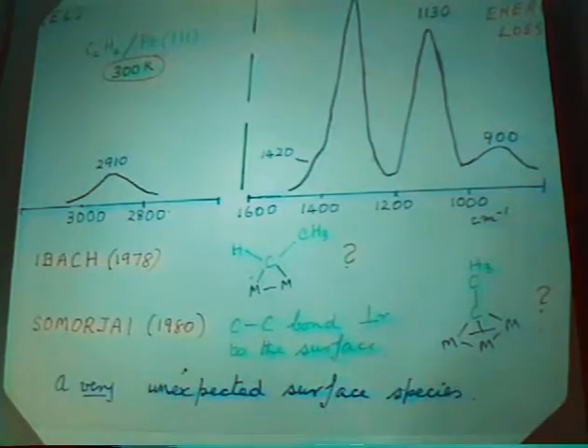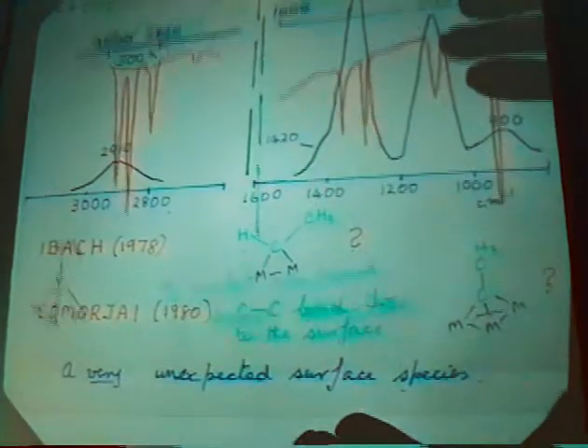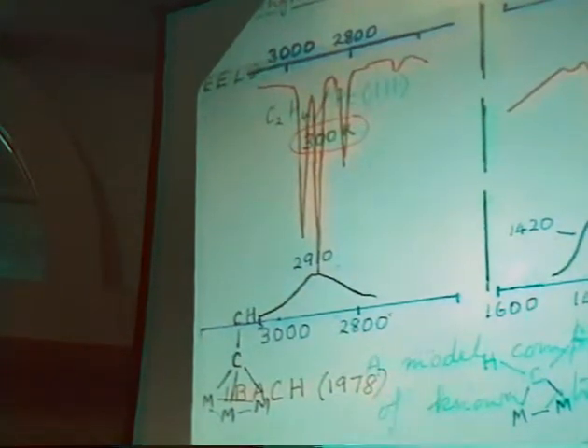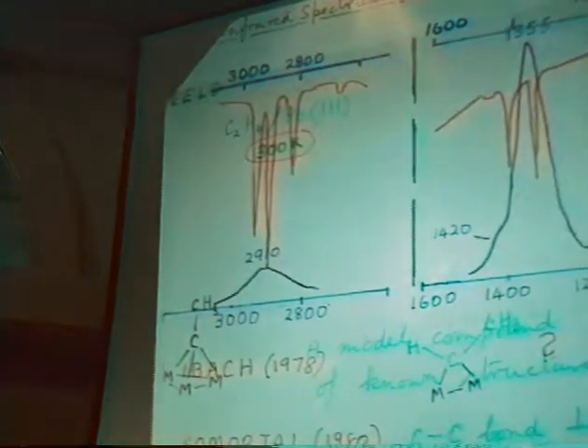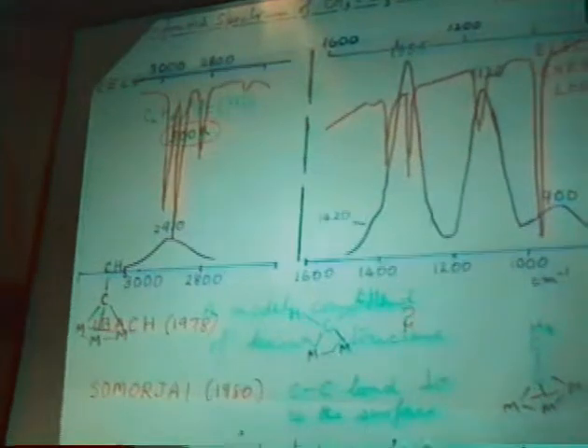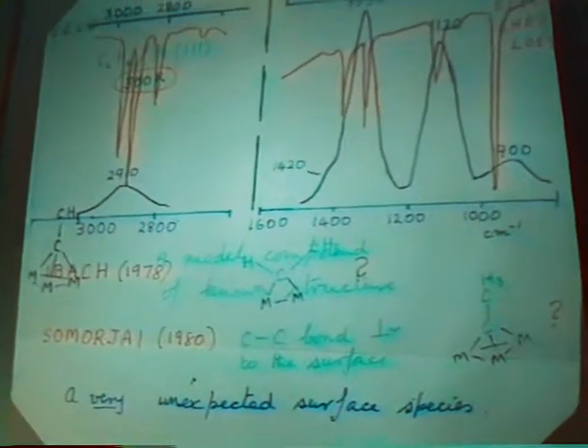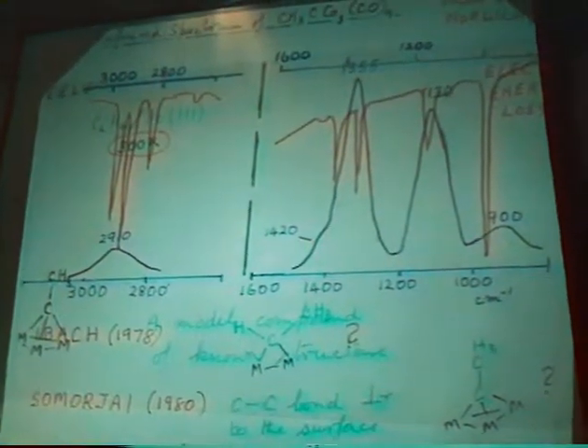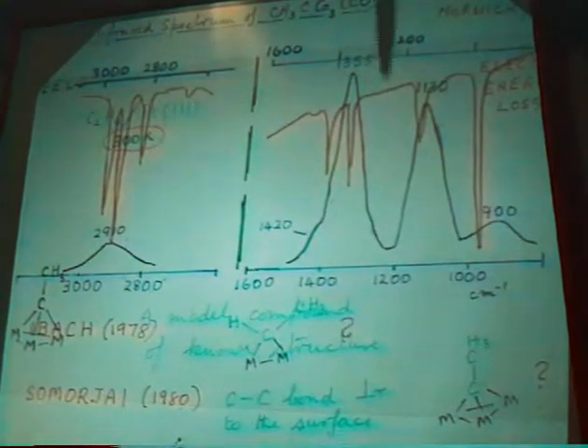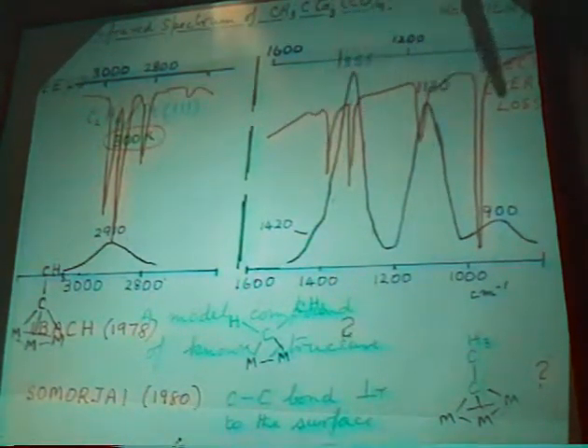And so I immediately retook its spectrum and superimposed it on the spectrum of the surface species. And you see there are coincidences among the absorption bands. The resolution is too poor up here to know exactly what you are. But some of the bands showed up on platinum 111 and others were missing. But of course, this is a complete spectrum. This is actually from a tri-cobalt complex, where there's no reason for the metal surface selection rule to be operating, so only some of the modes should be present on the surface. The question was, were these the perpendicular modes and these the parallel modes?